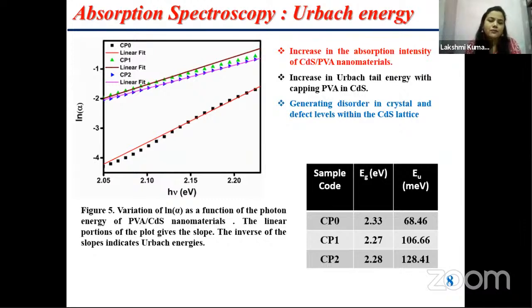As we have seen in our absorption spectra, the PVA capped system achieves more visible absorption. So here we find the Urbach energy. For finding the Urbach energy, we have plotted the variation of ln alpha as a function of photon energy, and the linear portion gives the slope, and Urbach energy is calculated by taking the inverse of this linear slope. From the figure we can see the increase in Urbach tail energy, which I have also mentioned in the table.